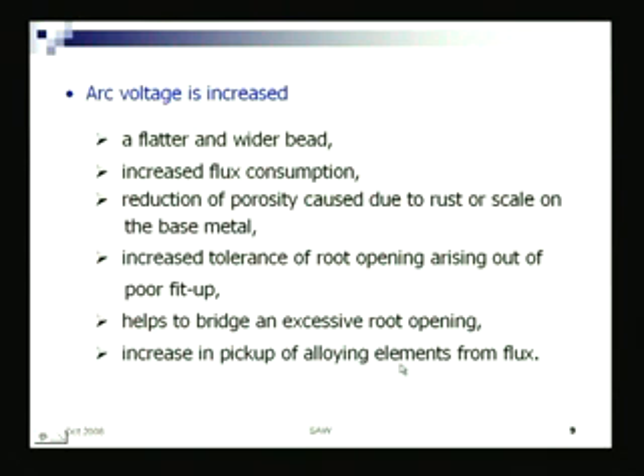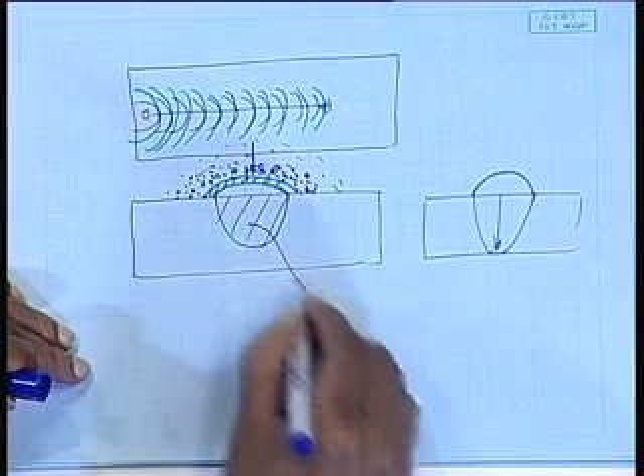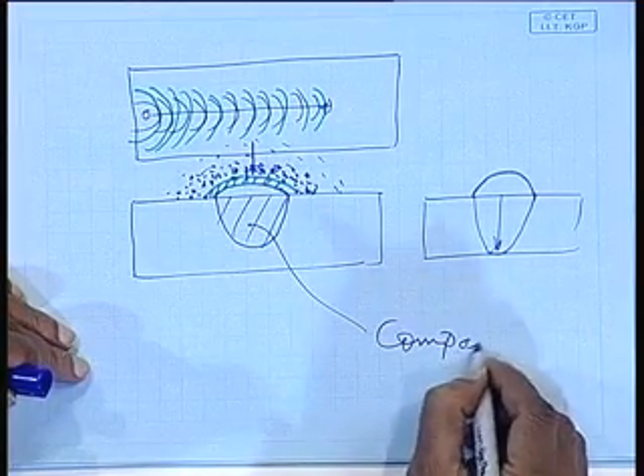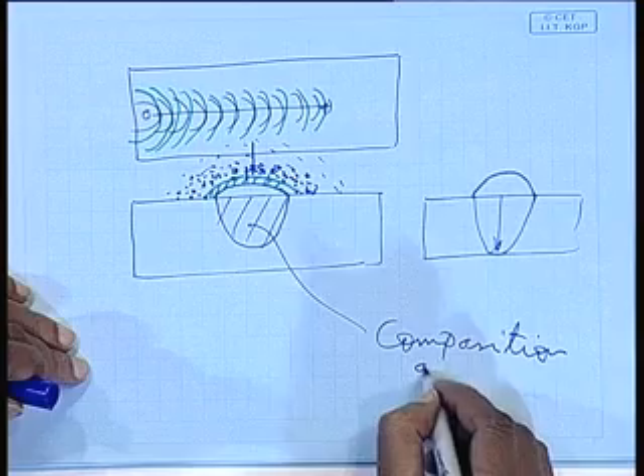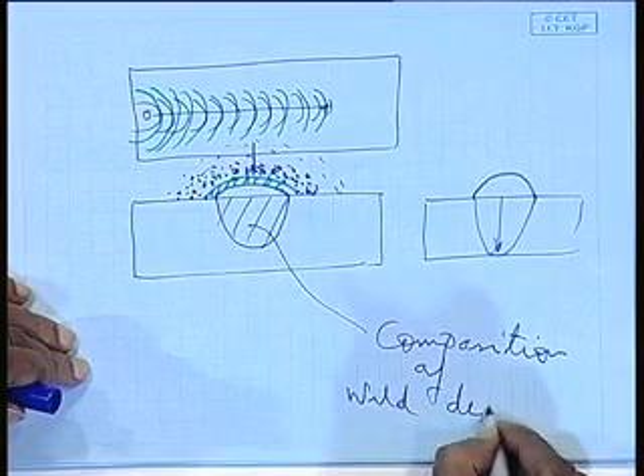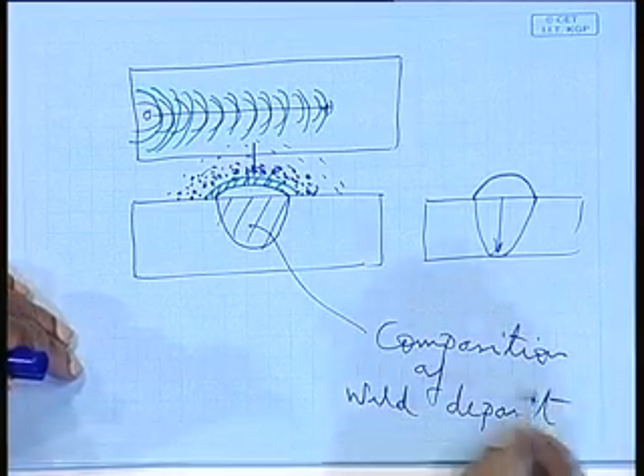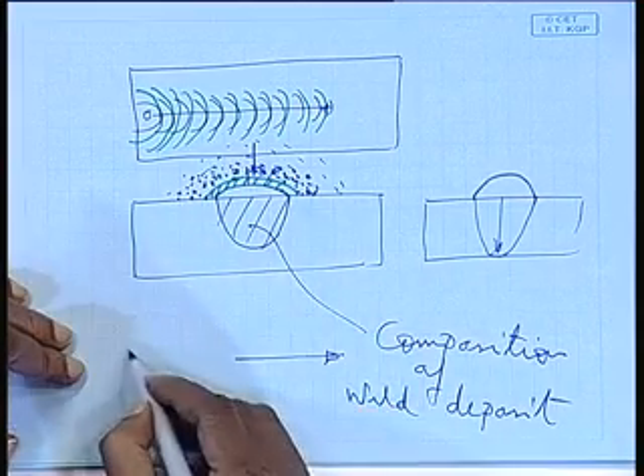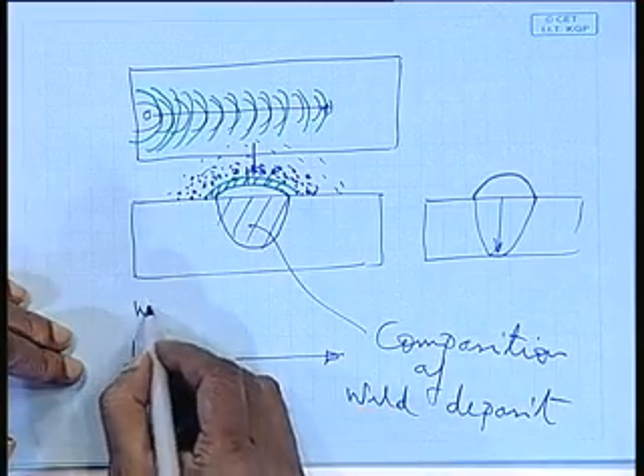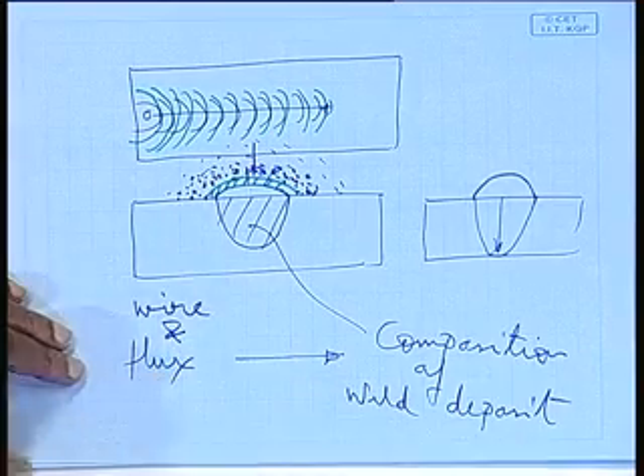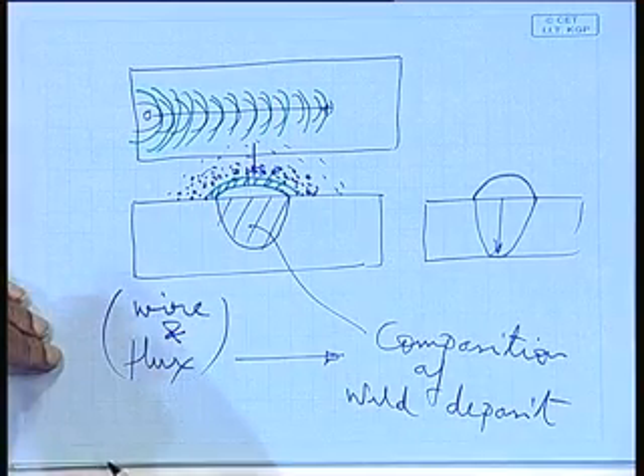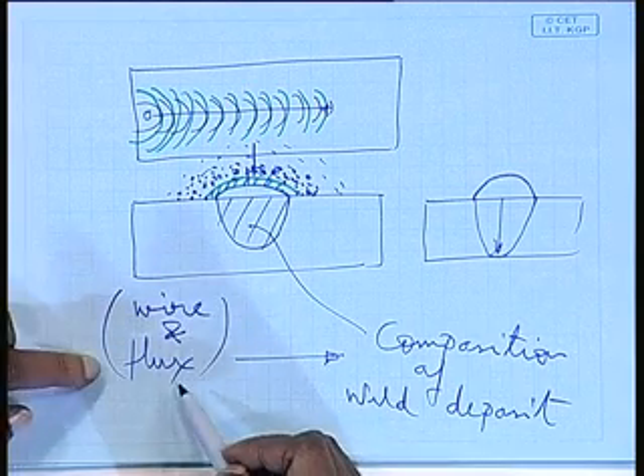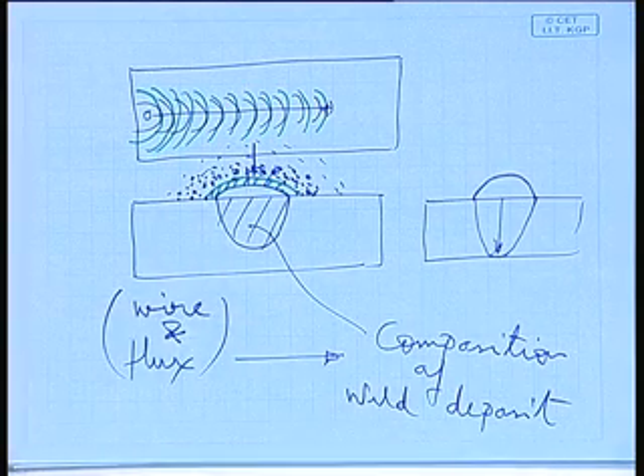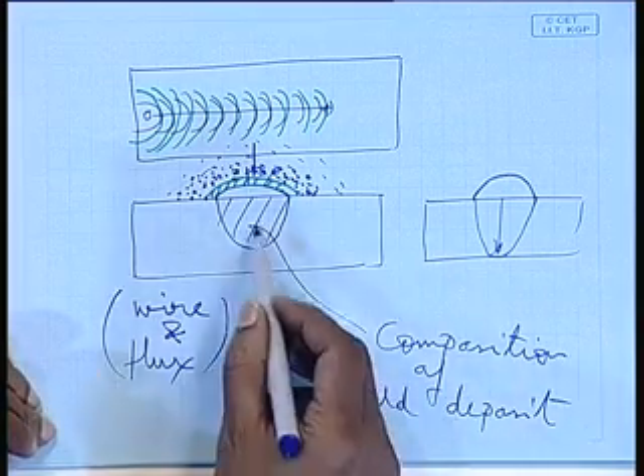Increase in pickup of alloying elements from flux is another aspect in submerged arc welding not available in other processes. The composition of the weld deposit can be altered by choosing a suitable flux, that means a suitable wire-flux combination. Wire-flux combination means the wire is the electrode, and the flux. For a particular wire-flux combination, I can change the composition of the weld deposit.